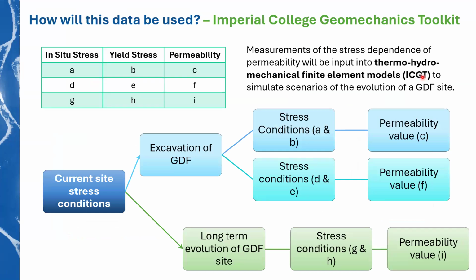How will this data be used? So we're trying to almost create a roadmap for our partners in Imperial College London. They have a geomechanics toolkit that allows them to simulate the GDF, and they can input lots of different parameters into this toolkit. So we're saying, for example, we have our current stress conditions. When we excavate the GDF, we expect the stress conditions to change to perhaps this value. So then those stress conditions would lead to this permeability value. Whereas if the stress conditions change in a different way, we know what permeability value that would lead to. So we're essentially giving our data as a roadmap for the modelers to then work out how permeability might evolve over potentially a long timescale up to 1 million years.